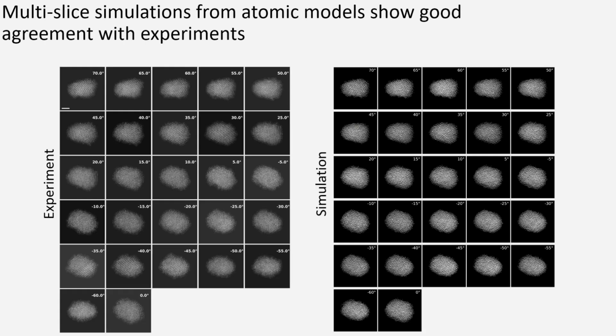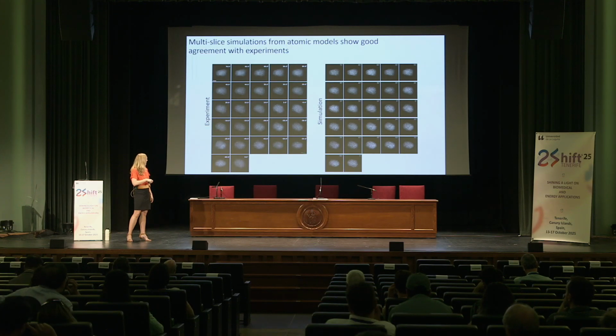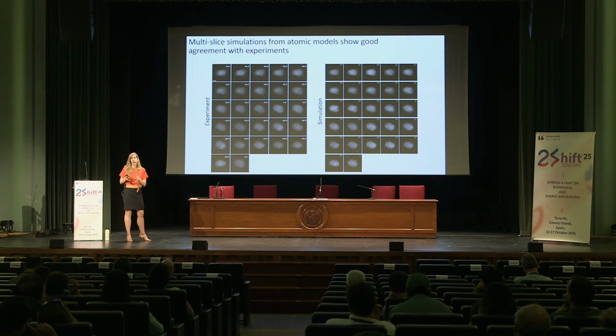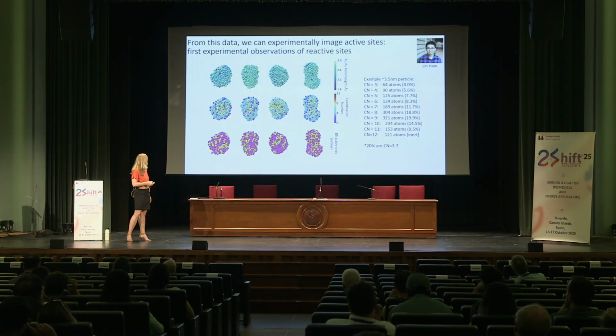And if you look at the experimental tilt series and then do the atomic reconstruction of what the 3D structure of your catalyst looks like, and then take that atomic reconstruction and back project it to each angle, you can see that that simulation or that back projection actually has amazingly good agreement with what we experimentally observed. So we know that this atomic 3D construction corresponds quite well to what we're experimentally seeing.